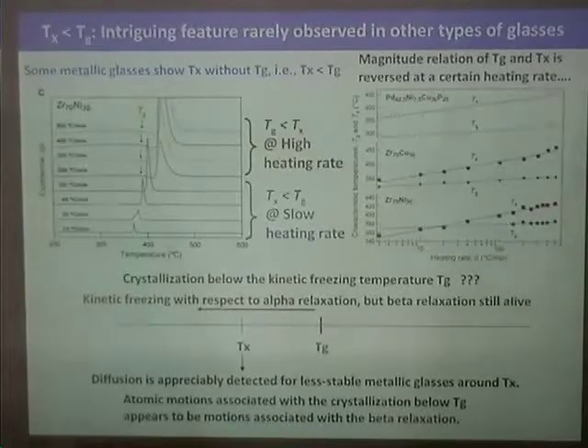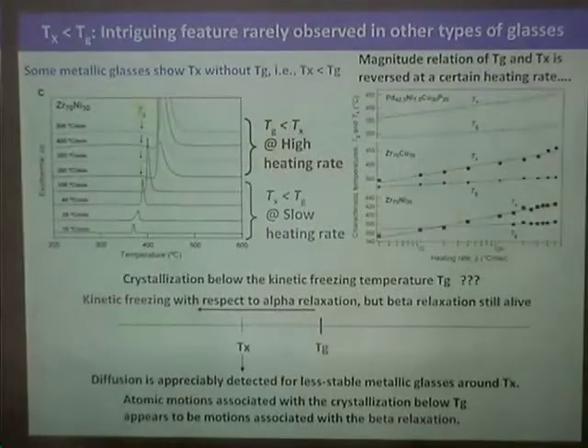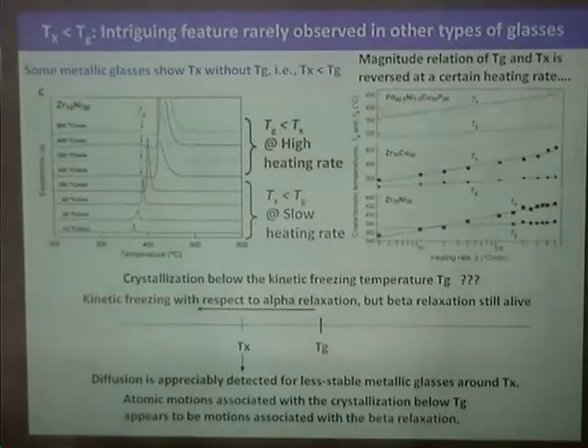The difference in slopes between Tg and Tx, isn't that a manifestation of the different activation energies? Yes, the apparent activation energy. The slope is the inverse of the apparent activation energy.